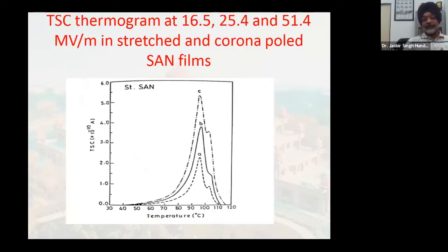Now this is the thermally stimulated current studies in the case of stretched styrene acrylonitrile films. Now look here. Thermally stimulated current studies have been done, and poled films are subjected to them. When the temperature is raised, we find that all the films show a peak at this particular temperature, at around 90 degrees centigrade, 95 degrees centigrade. Then there was another peak at around 102, 103.